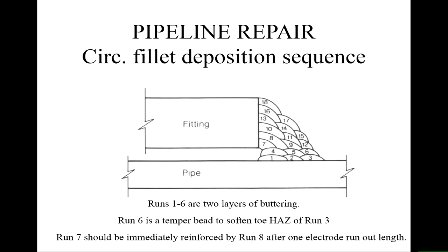So you'll have a sequence of welds which are put in the welding procedure specification. So in this case it's 18 weld passes to actually make that joint of the pipe to the fitting. And runs 1 to 6 have no joining, they're just the buttering runs. And run 6 is a tempering run, so that's this one here. So that's trying to make the microstructure in runs 1 to, well, run 3 basically, as good as you can. It softens any hardness you might get from martensite formation in that first run.